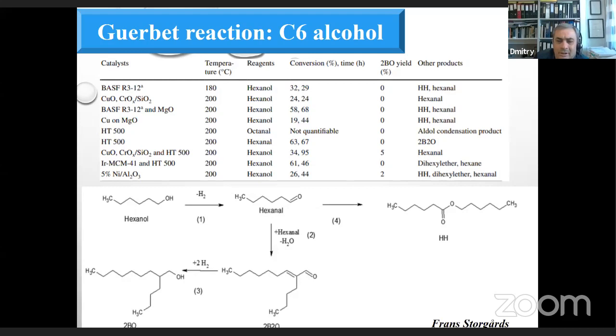And the reaction temperature had to be approximately 200 degrees C. Conversion was not that high, and the duration of catalytic experiments was pretty long. So we had all those experiments in the batch mode.